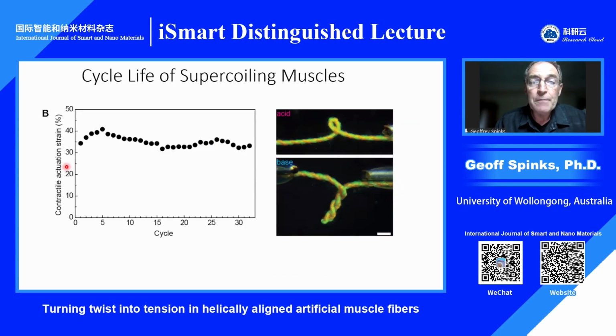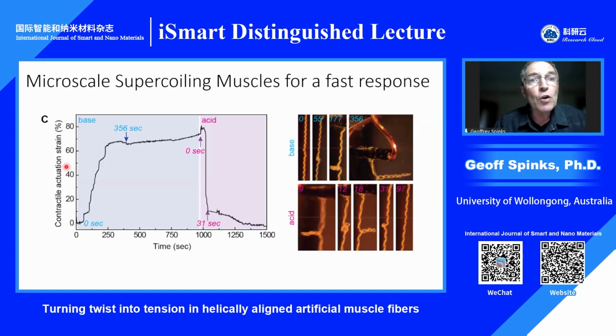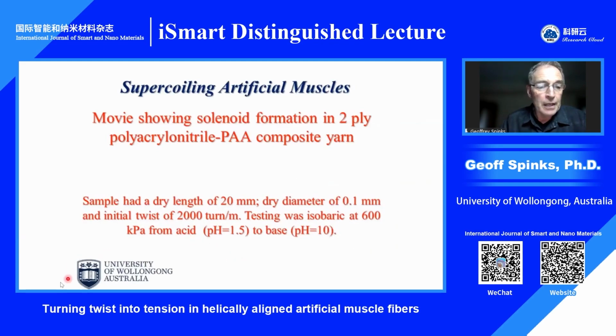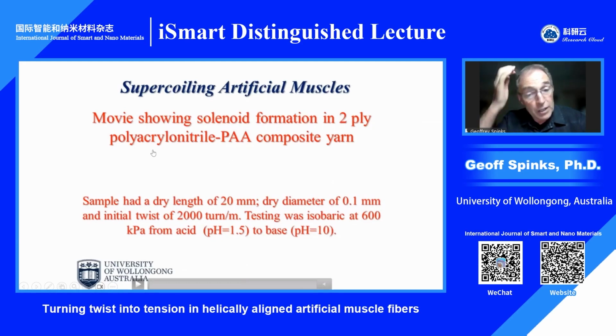Cycle life was okay. Now, you probably noticed that these things all work very slowly because we're using acid and base for swelling. So my student went back to the electrospinning and produced some thinner fibers and was able to produce responses in the tens of seconds regime. So it certainly does depend on diffusion kinetics. Here's an example, I think a particularly beautiful example of electrospun polyacrylic acid and electrospun polyacrylonitrile, 2-ply twisted together.